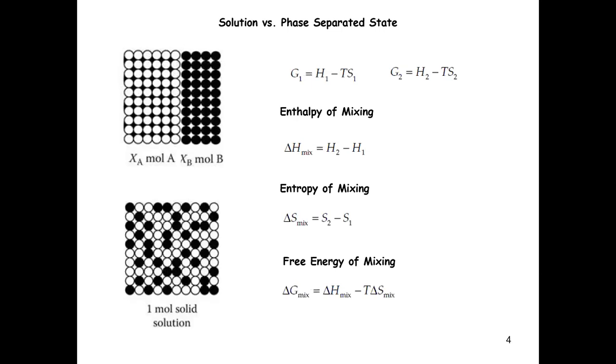No, it won't favor the mixing. Demixing. It's going to favor the demixing state, right? So if this enthalpy of mixing is greater than 0, from the interaction energy point of view, does the system favor the mixing state or the demixing state? Demixing. The demixing state, right? Because mixing increases the interaction energy, right?